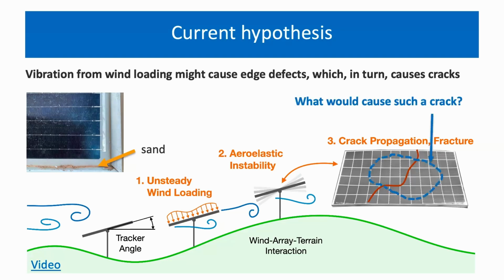However, we also see cracks where you have a circular shape just in the glass, which doesn't touch the edges at all. And so we don't have an explanation for that yet.